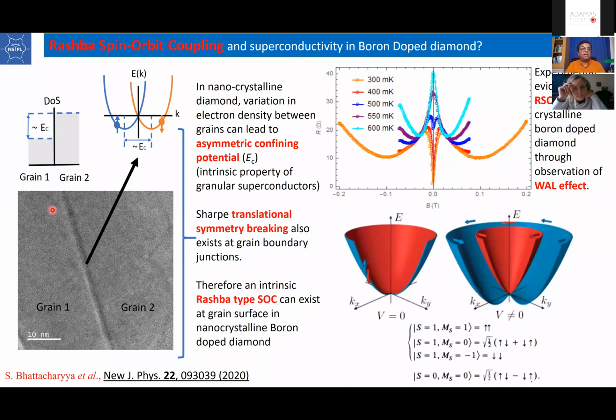Now, if you look at the grain boundary again, grain 1, grain 2, these are superconducting grains separated by a grain boundary region, and you have charge accumulation in this grain boundary region. And there's a model called the Edelstein effect, which is similar to Rashba spin orbit interaction. So what you do is sharp translational symmetry breaking. It takes place here because the potential is broken at the boundary, and you can see the effect like Rashba type spin orbit coupling. Now, what is the proof?